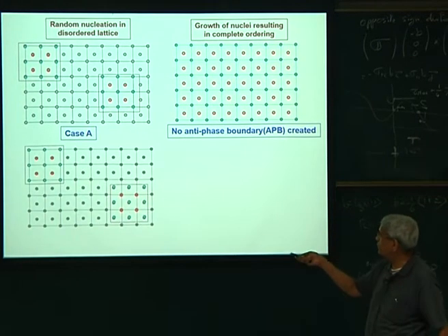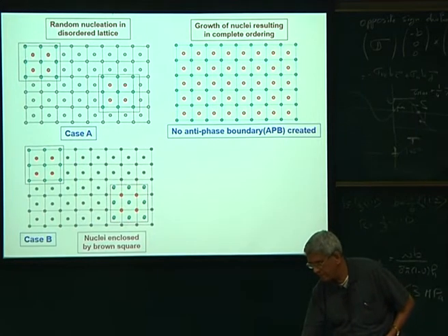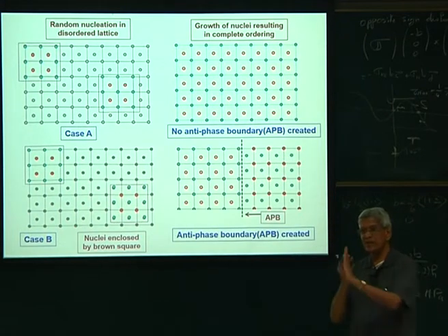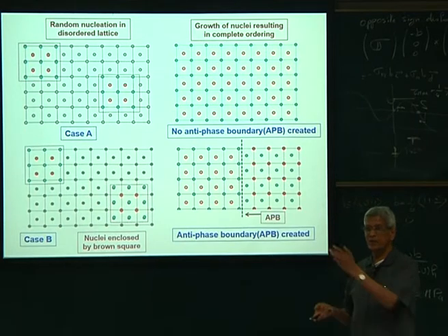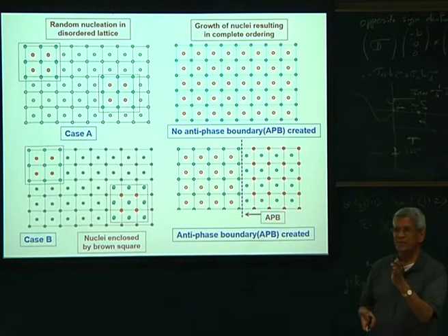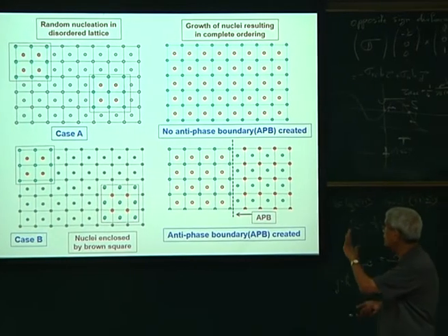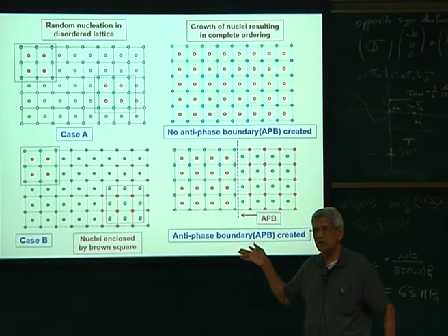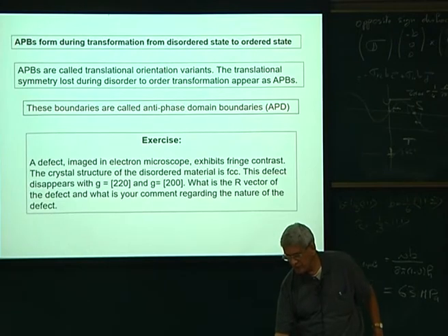And in this other case, when they join together, there is a fault, a shift. This shift, if you look at the periodic conditions, is a shift of pi. That's why it's called the antiphase boundary or pi boundary. These are all the names used because of this shift. So this sort of boundary is also a shift, because of which, if it is inclined, it will give rise to a fringe contrast.